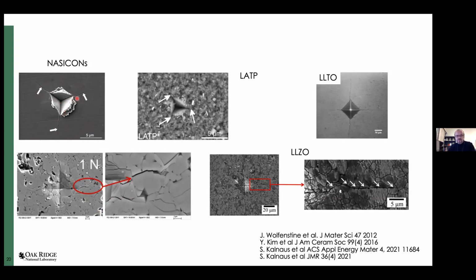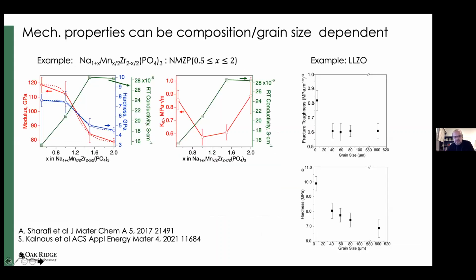And if you do these tedious, almost sadistic experiments of doing this many times and measuring the crack lengths, you can numerically calculate the fracture toughness and get exactly those values that are shown in the table. Most of them are 1 megapascal square root of meter or less. So this sounds like we're almost doomed, because all of the materials fracture, all of them will let lithium dendrites go through, deposit into those fracture surfaces. But there are actually some ways, there is a glimpse of hope. There are some ways to impart some ductility into ceramics.